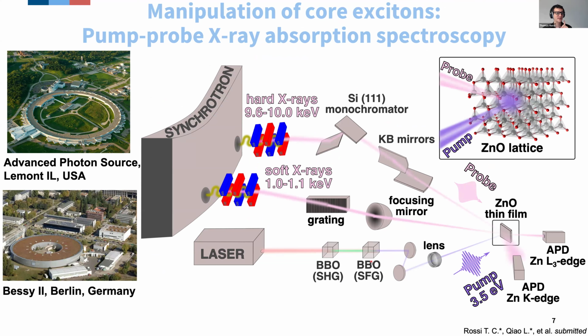But this is not sufficient because you also need to worry about the penetration depths of your films. For both X-ray experiments, we match the thickness of the thin film with the penetration depth of the pump laser, so that also in the depth direction, you only probe atoms that have been excited by the laser pulse. Okay, that's great. Thank you.